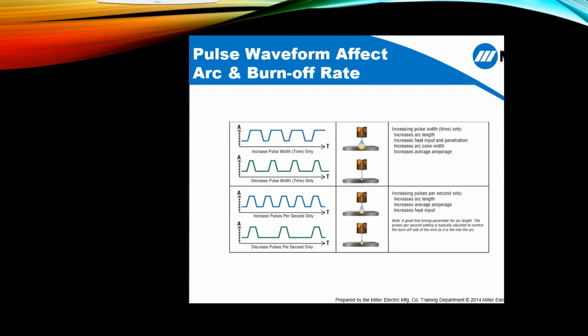When we're welding on really thin aluminum, some of these auto body panels or automotive parts might be down around 18, 20 gauge thick aluminum, and it's very thin. You have to be very cautious of heat input. One of the things you'll notice is when you get down on that lower end and you're using a low or slow wire feed speed, you're looking to transfer fewer droplets, so you're going to see fewer pulses per second. And when we get into the video that's coming up, you can actually hear that.